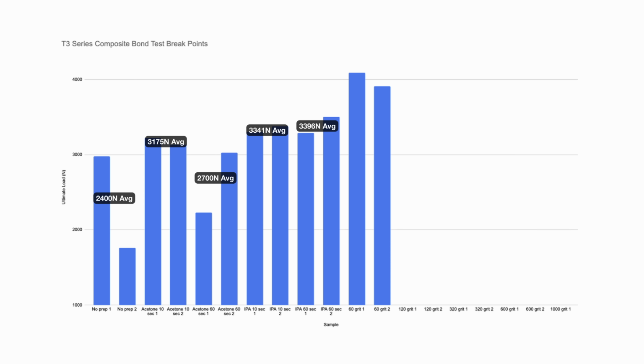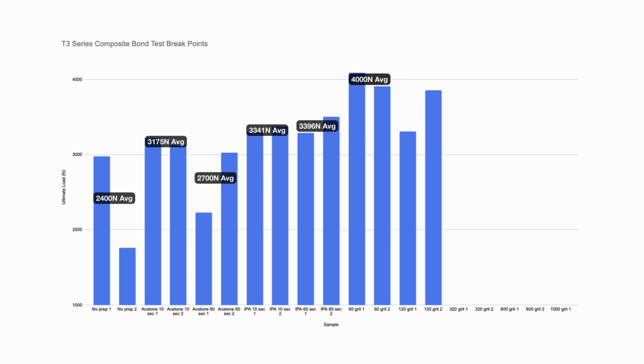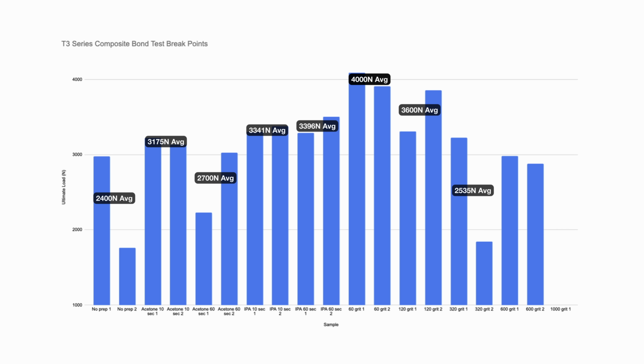Sanding is where it gets interesting. My first 60 grit sanding test performed excellent, averaging around 4,000 newtons. 120 grit had a little more deviation and averaged lower at around 3,600. Then it falls off a cliff. 320 grit had enormous deviation between 3,200 and 1,800 newtons. 600 grit averaged 2,900, and the single 1,000 grit test I ran was a pitiful 1,400 newtons.